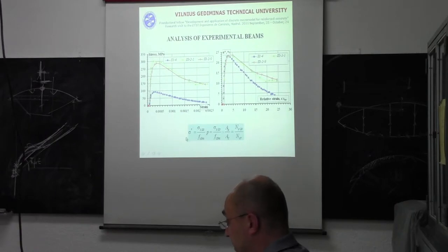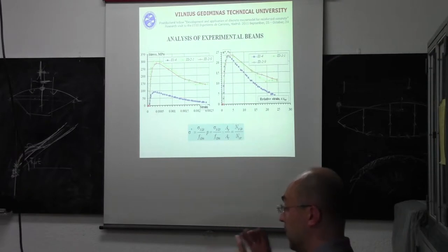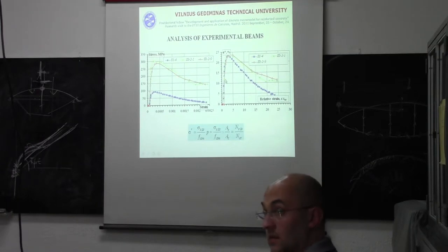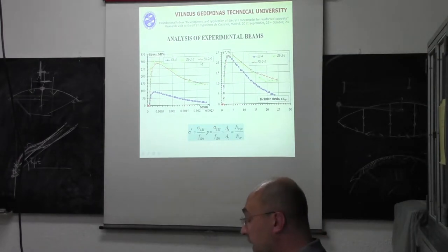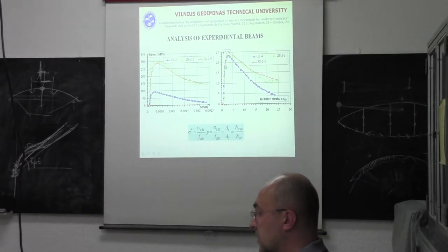if we normalize these diagrams as shown here, as the ratio between axial force in reinforcement due to tension stiffening and the cracking resistance of the whole concrete section. Then we obtain that practically, independently of reinforcement ratio,